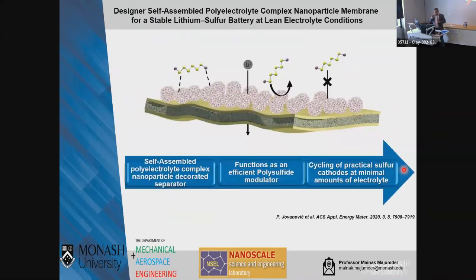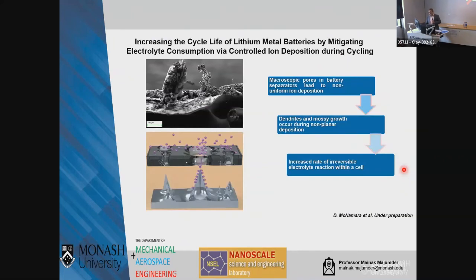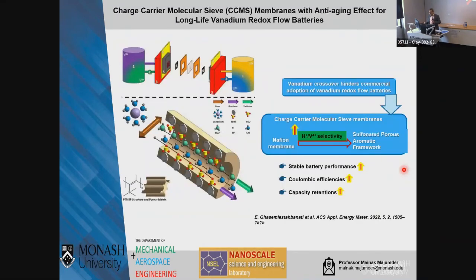A bit more research we do on the separator side of lithium-sulfur batteries. This is Petar's work. We functionalize with self-assembled polyelectrolytes, enabling lithium ions to go through and rejecting polysulfides. And then there's also a project ongoing on protecting lithium metal by specialized coatings. Again, a work in which we try to make a membrane for vanadium redox flow batteries, where instead of using a Nafion membrane, we used a composite membrane made from sulfonated porous aromatic framework and a microporous polymer, with some interesting properties in terms of anti-aging and charge carrier properties.